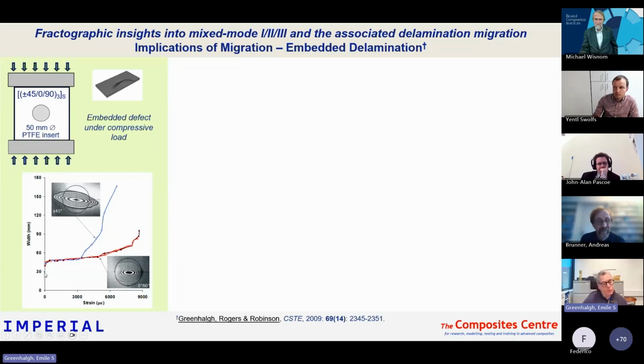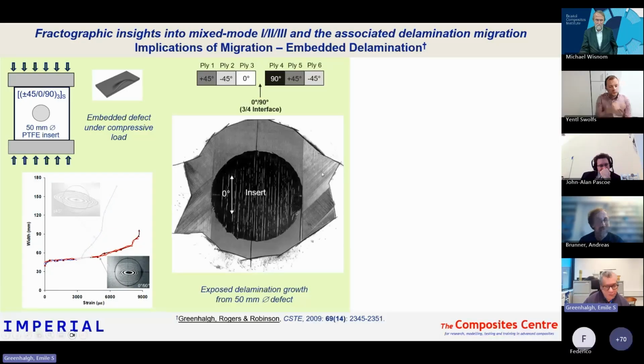So it's this graph here, which is showing the damage width against applied strain on the laminate. In the case of the ±45 interface, so this is between the fifth and sixth plies, it basically would jump into the 90 ply and then shoot along, and this is why the damage growth was quite rapid. But in the 0/90 ply interface, this was the process that occurred. So all this migration process was really inhibiting the transverse damage growth. And we were getting up to 8,000, 9,000 microstrain before final failure occurred.